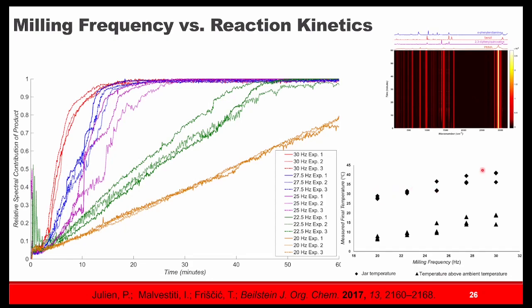One thing that we did with this also is look at the temperature at the reaction endpoints, because we suspected the temperature might have a pretty significant role here. Again, we're not hitting any crazy temperatures to get the reactions to go. The highest that we measured, I think, is about 42 degrees Celsius in the milling jar after this hour-long milling. So it's not generating massive amounts of heat.